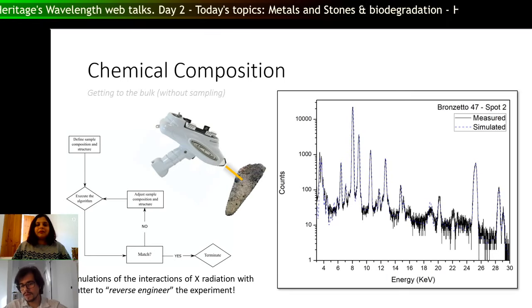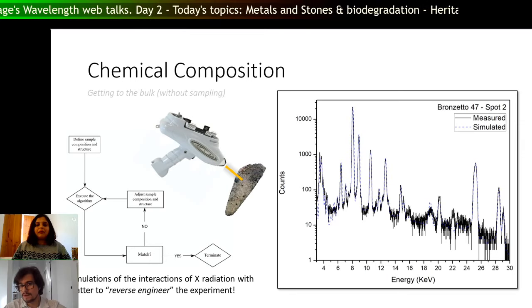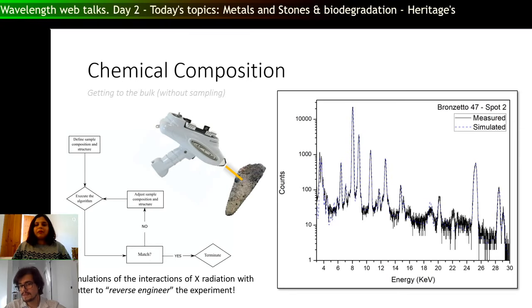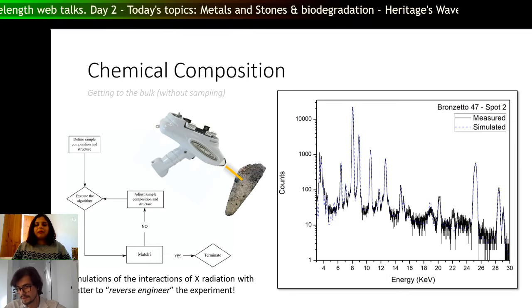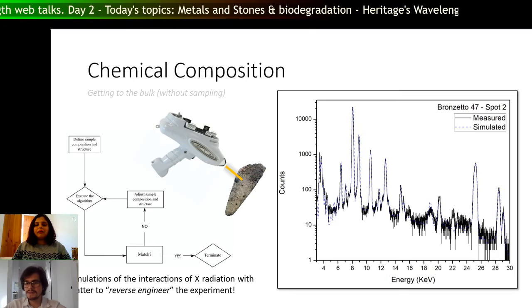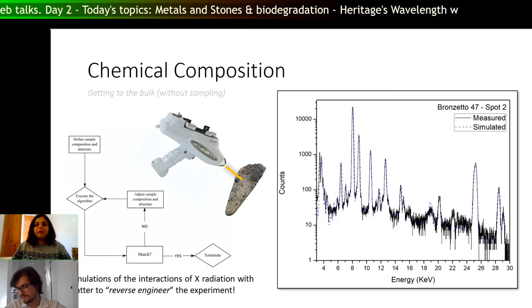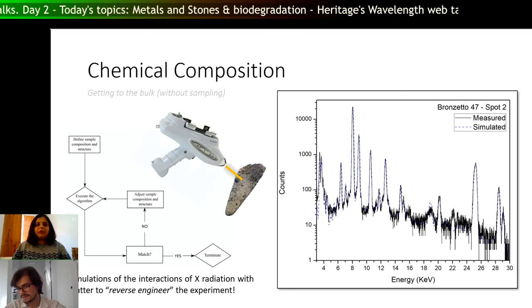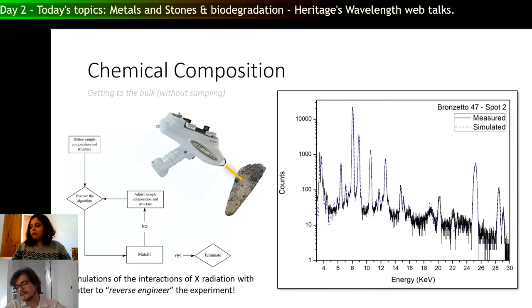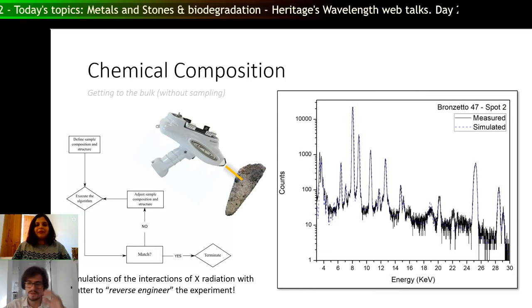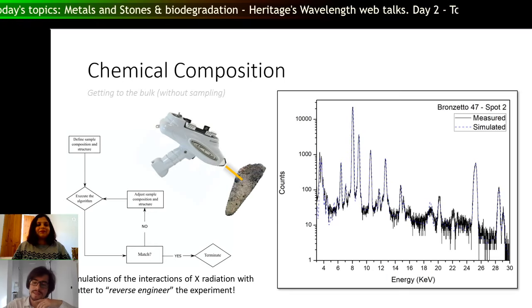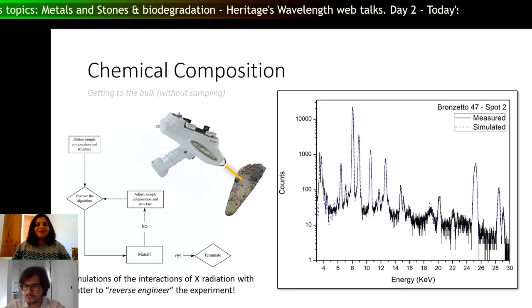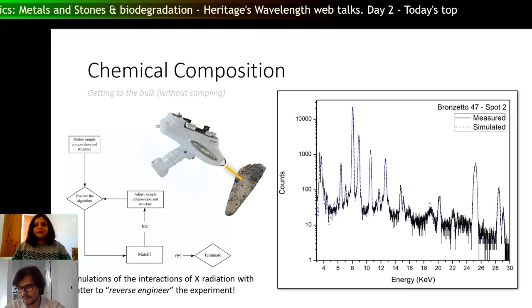So with that, you can look at it and you're like, there is a lot of copper. I can see some silver here. So I can start guessing what this silver, by the way, is from the tube. Oh, it's not silver. Sorry, this is tin. This is tin, around 25 kilo electronvolts. So you can start with an initial guess. So I know this should be a tin copper alloy at least.